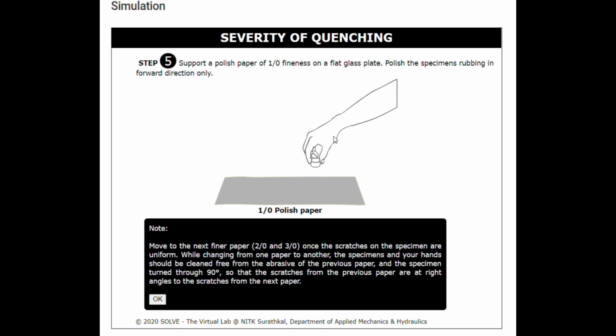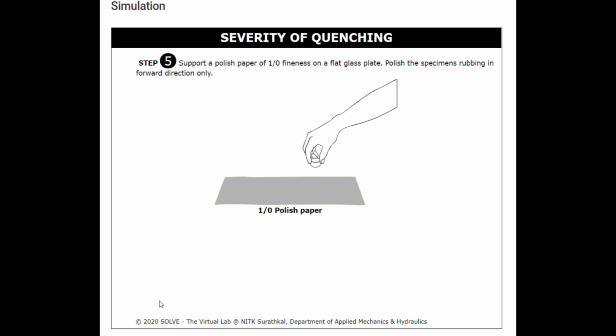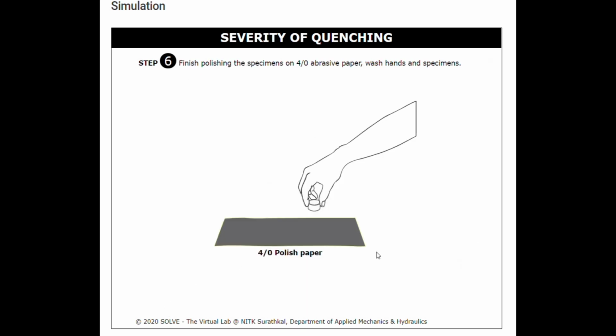While changing from one paper to another paper, the specimens and your hands should be cleaned, free from abrasive of the previous paper, and the specimen turned through 90 degrees, so the scratches from the previous paper are at right angle to scratches from the next paper. Then we finish the polishing of the specimen on 4/0 abrasive paper. Then we wash hands and the specimens, polishing only in the forward direction.